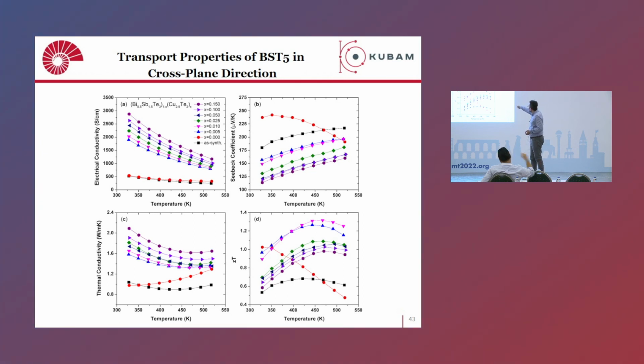Now, you can see that this is bismuth antimony telluride, again, no copper telluride addition. This is as-synthesized. The main difference between the black and the red is this. In the red, you may remember I told you that copper telluride is added by 10-minute ball milling after we synthesize this material. Now, we synthesize this material, then 10-minute ball milling without any copper telluride addition, and the other copper tellurides are also done in the same way, with 10-minute ball milling. So we wanted to show what is changing here, right?